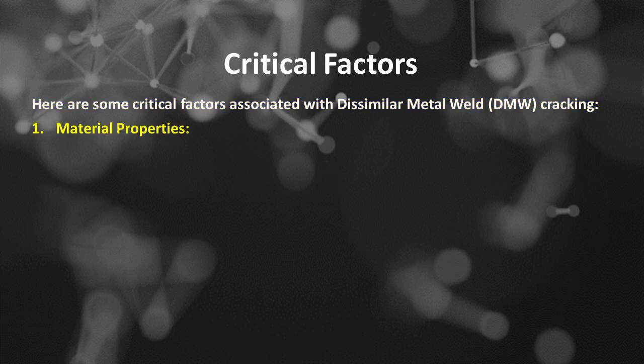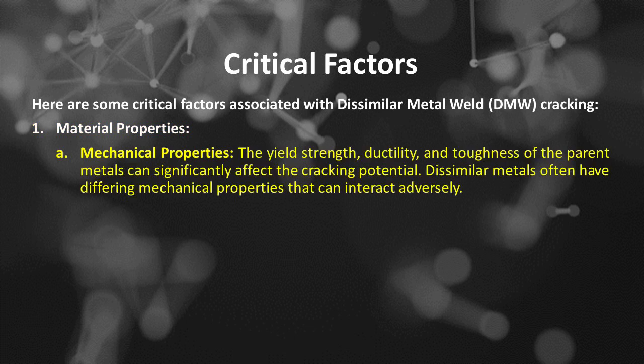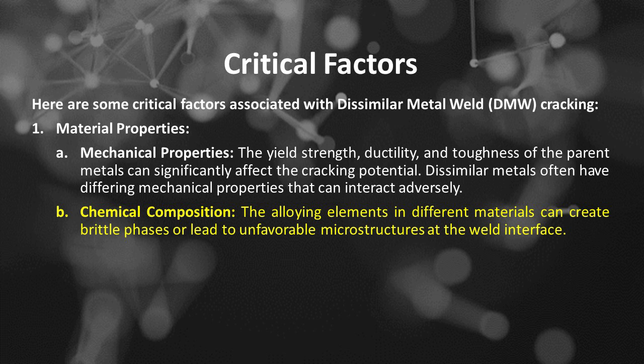Number 1 is material properties, such as the following. The first is mechanical properties. The yield strength, ductility, and toughness of the parent metals can significantly affect the cracking potential. Dissimilar metals often have differing mechanical properties that can interact adversely. The second is chemical composition. The alloying elements in different materials can create brittle phases or lead to unfavorable microstructures at the weld interface.